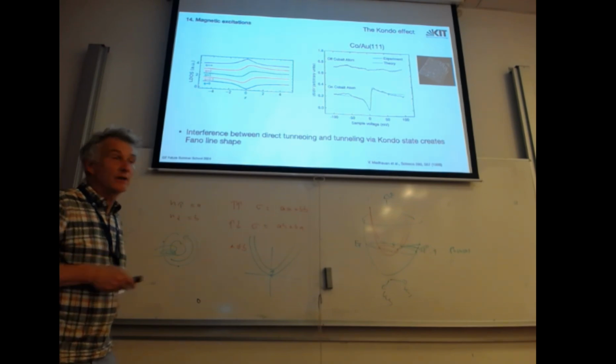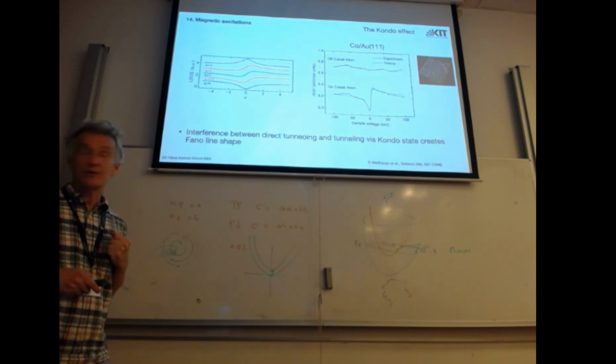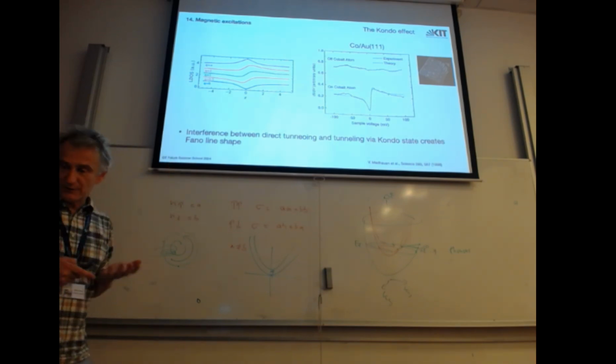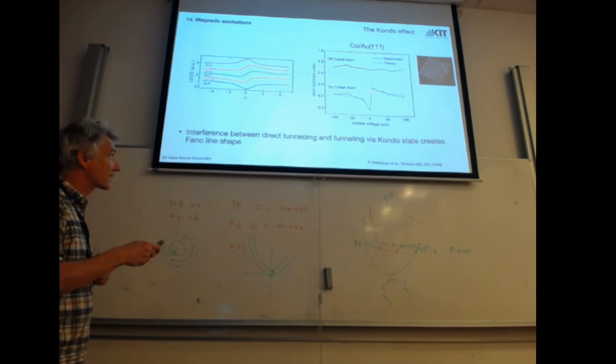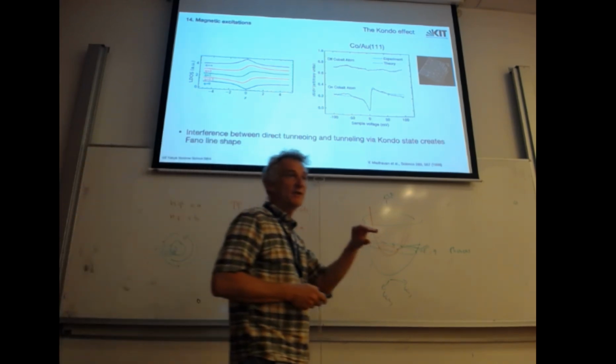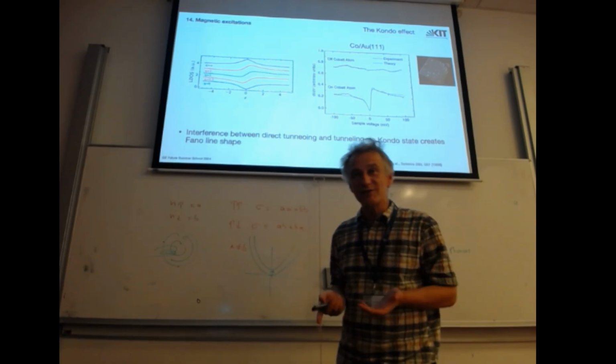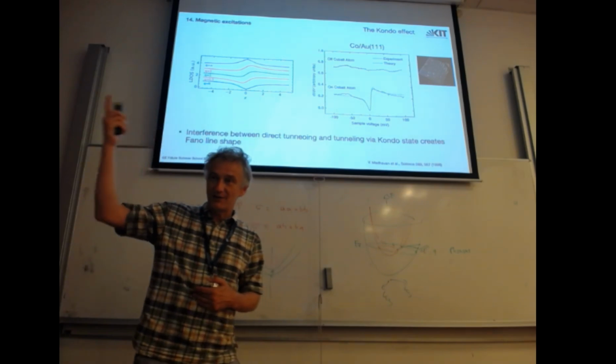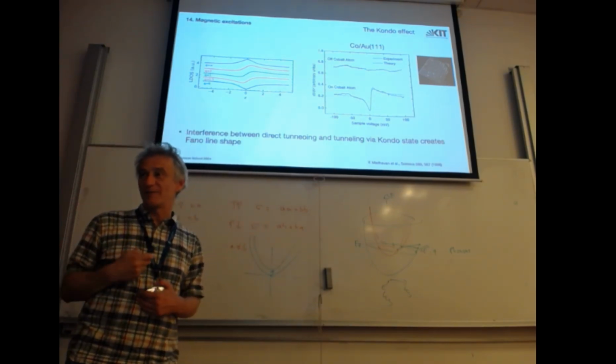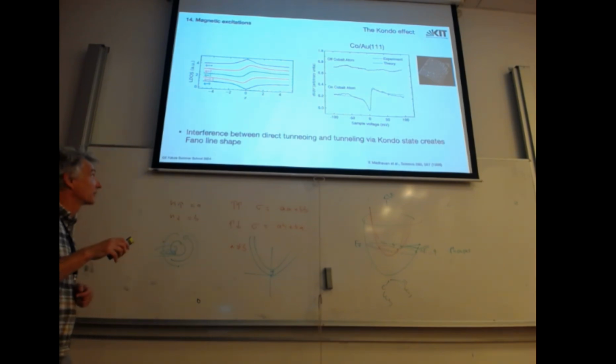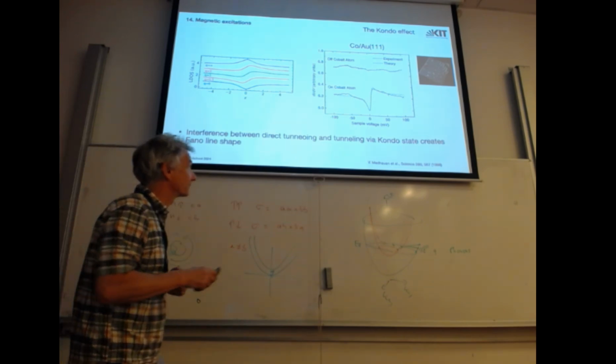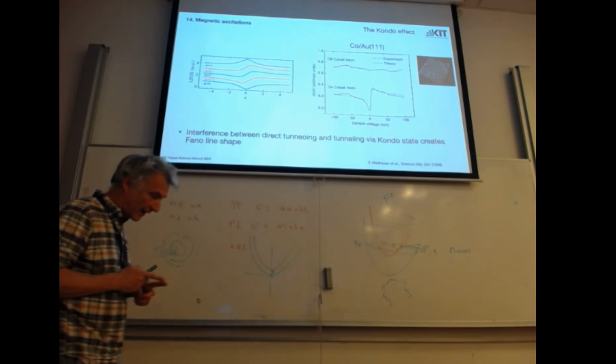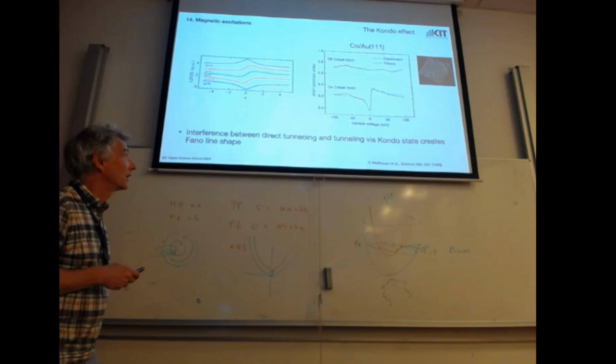And what you should see is a peak, this localized peak at the Fermi energy, but we see wiggles. The reason that we see this kind of Fano shape is because it's a discrete state living in a continuum, and we have interference between tunneling from the tip directly into the gold, or from the tip into the Kondo cloud and into the gold. There are two paths. There's a phase difference. Depending on the phase difference, this can look like a peak, or this swinging, or a dip. This is a phase argument. So there's an interference of the electron. You can choose two paths to go from the tip to the sample.